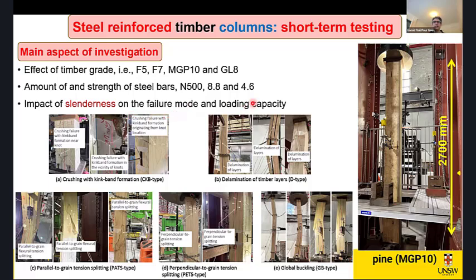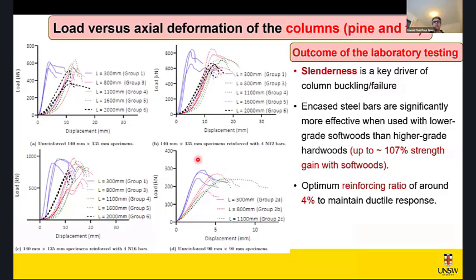And so far, we have tested columns up to 2.7 meter in length, and we are planning to do additional tests on columns up to 3.6 meter long in the next few months. So a range of failure modes you see is starting from crushing, development of kink bands, to, let's say, splitting or buckling and secondary bending of the beams. These are sample load versus displacement.